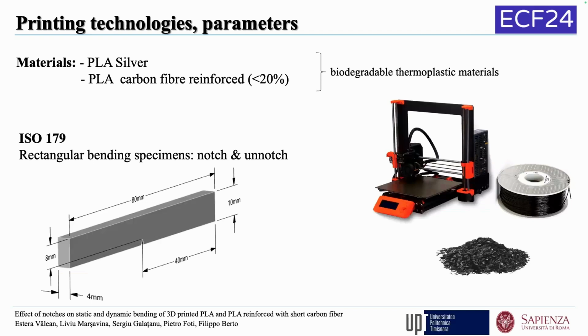So we use a commercial 3D printer made by a Czech producer, a Prusa printer. PLA and PLA reinforced with carbon fibers, less than 20%. The dimensions of the fibers: the medium diameter was between 10 and 15 microns, and their length was around 250 microns. We print because we want to do impact tests. We chose the shape of the specimen according to ISO 179, which is the instrumented impact recommendation.